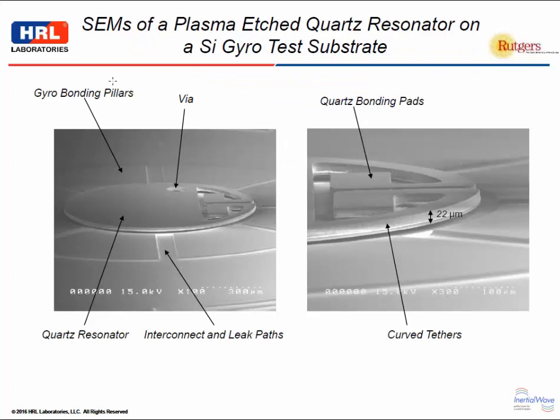So once we had that design in place, we did some test fabs on some wafers just to see whether we could bond this thing and make it to the design. This shows the SC-cut resonator bonded to a test silicon substrate. And you can see these cutouts that we put into the pillars for bonding the gyro structure to. And these cutouts serve two purposes. One is to allow us to bring in interconnects to the quartz resonator here, and interconnects for the heater and the RTD that we had buried underneath the quartz resonator. You can see here the 22 micron plasma etched profile. It's very clean. This is a doubly rotated crystal, so you'd expect if it was wet etched, you'd get a lot of different angles on the edge. Nice and clean structure with the tethers defined.